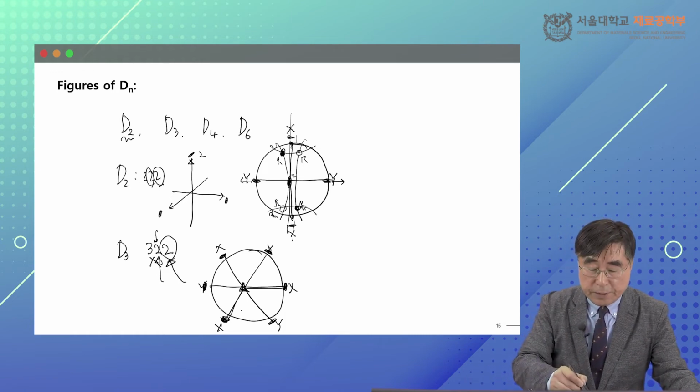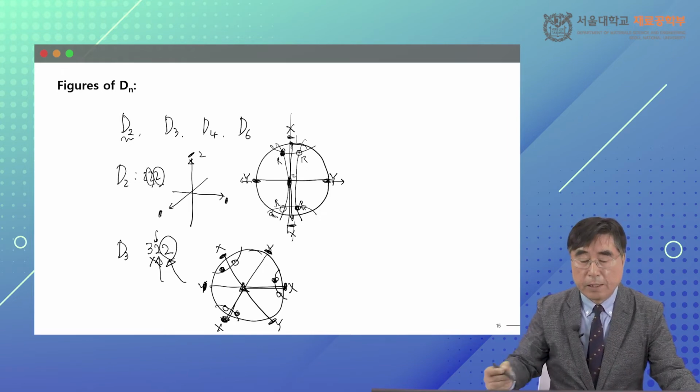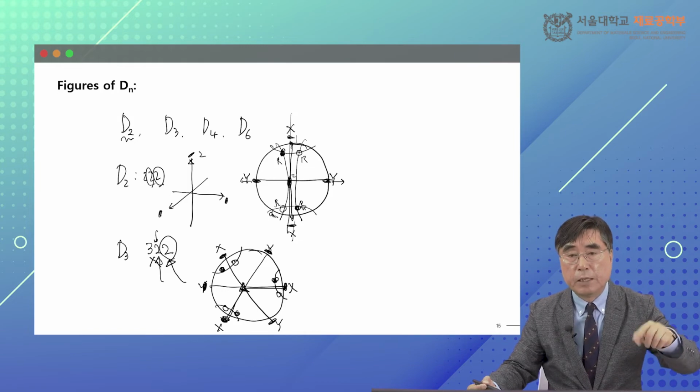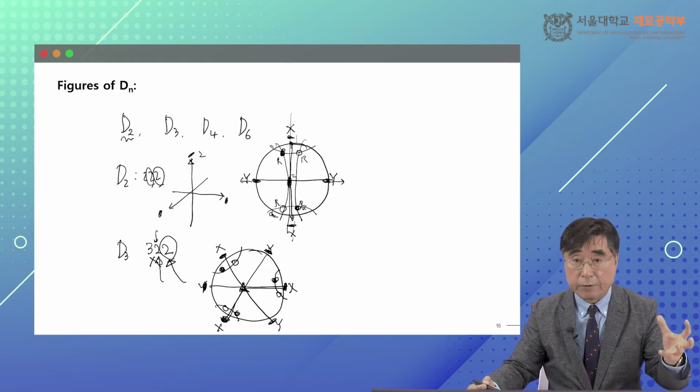Okay, now symmetry-wise, if I have a general pole here, then the threefold generates here, and this threefold generates here. Now this x-axis operation generates a down pole in here, and a down pole in here. This is all rotation. So even though it's upper pole and down pole, it still has the right-hand operation.